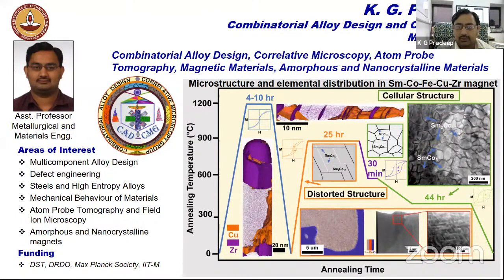My group basically works with correlative microscopy, where we try to combine different microstructural aspects together with their local atomic chemistry. So you can see in the current schematics, for example, of a samarium cobalt based magnet, a microstructure as a function of processing and how the microstructure evolves together with the defect structure. In the atom probe tomography, you can nicely map the local enrichment or local partitioning of these chemical species. For example, copper in the orange color and zirconium in the purple color. They form nice nano platelets if it's in an ordered way, or globular bulk clusters if it is in a disordered way.